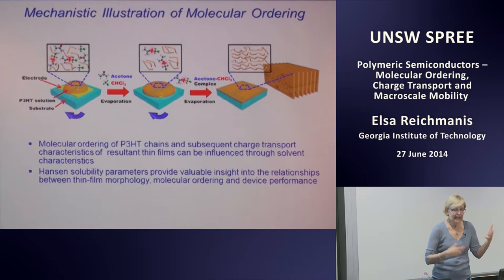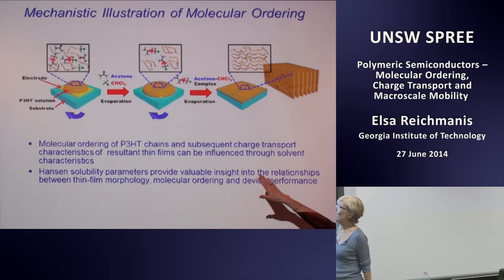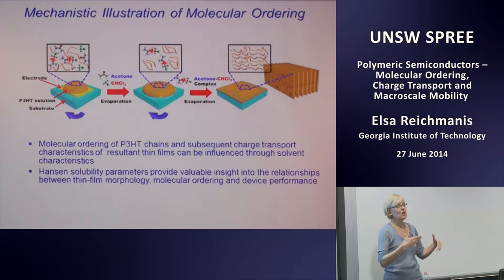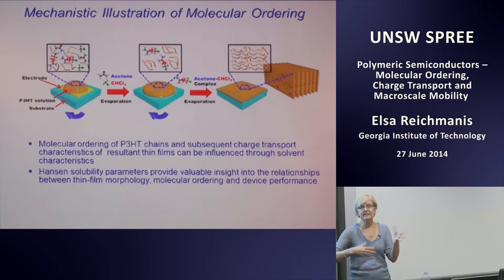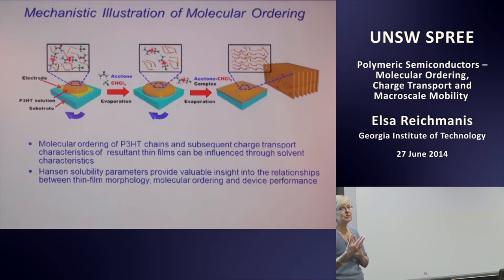All right, and in particular with the acetone case, we have a randomized network of polymer chains, which as solvent is evaporating, the proportion of acetone and chloroform is changing to one which is less advantageous for P3HT, and that helps to induce aggregation and ordering in the polymer system, which then leads to improved charge transport.